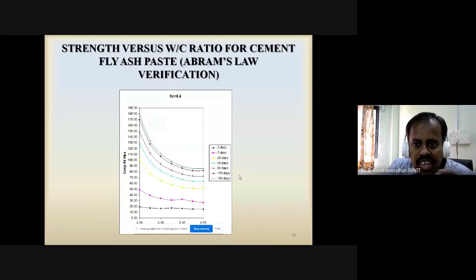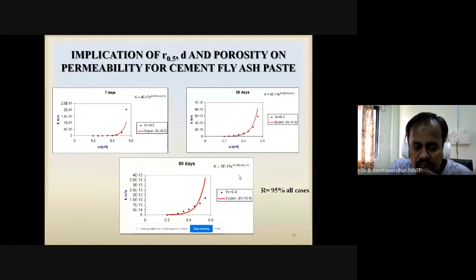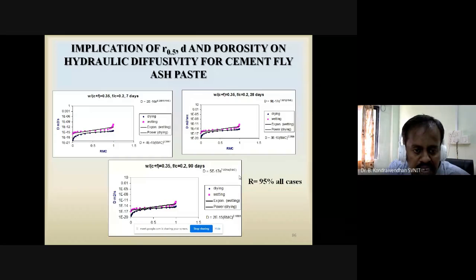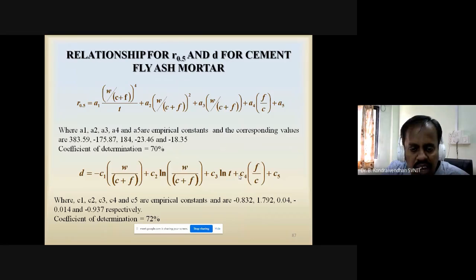So this kind of work has been carried out in the case of cement fly ash paste, and we have determined the permeability also. Then again we plotted the permeability versus water-binder ratio. This is also following the same trend as mentioned by T.C. Powers et al. We also determined the hydraulic diffusivity for both wetting and drying cycles. This is also following the same trend as mentioned by Hall et al. For the hydraulic diffusivity, we have determined both wetting and drying cases, all following the same category.